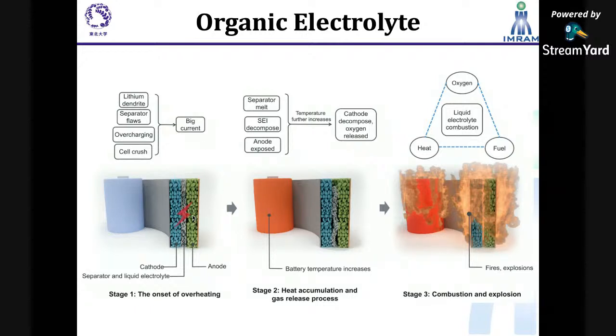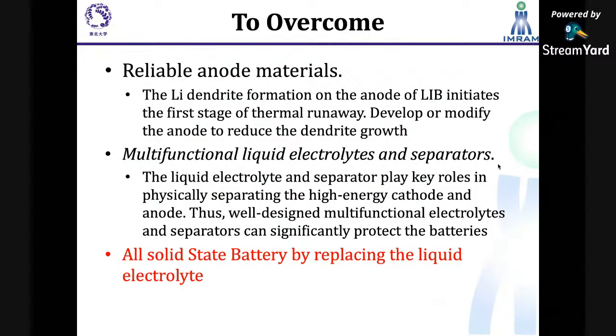When there is a big current, the cathode gets decomposed. Decomposition of the cathode means lithium nickel cobalt manganese oxide or lithium cobalt oxide. They are all oxide based compounds. When the cathode material decomposes, oxygen gas is released from it. This oxygen, as we all know, is highly flammable, and when it reacts with the organic liquid electrolyte, the heat generated between the oxygen and the organic liquid makes it start to burn or explode. This is the reason the liquid electrolyte is not stable and not safe in the present generation lithium ion batteries. So how do we overcome this?